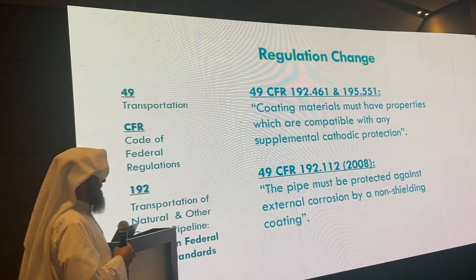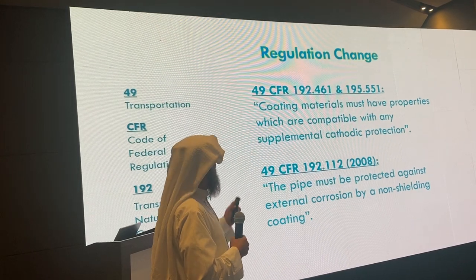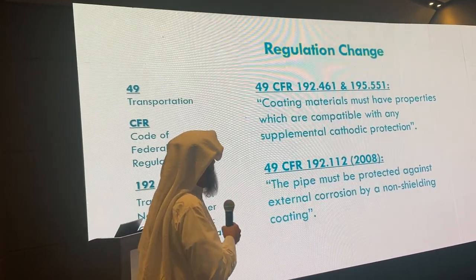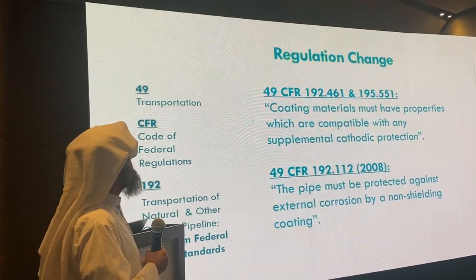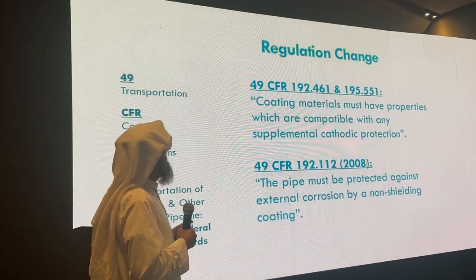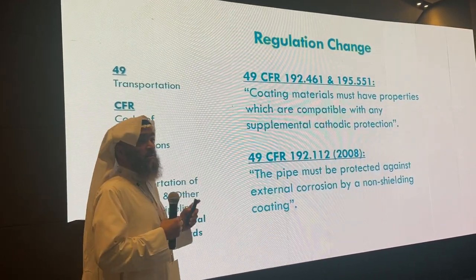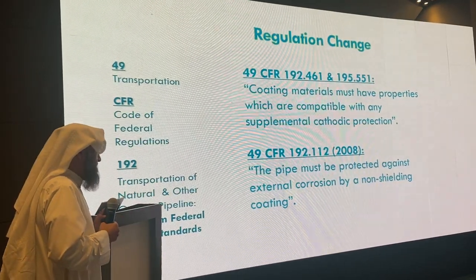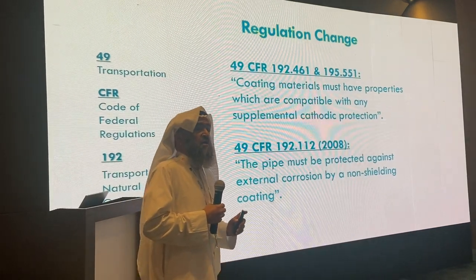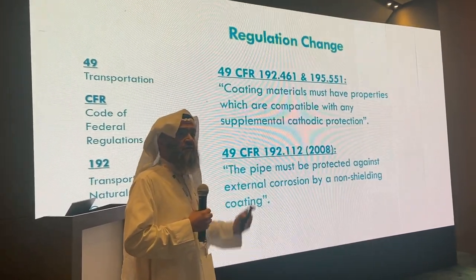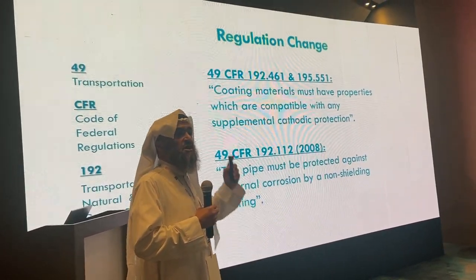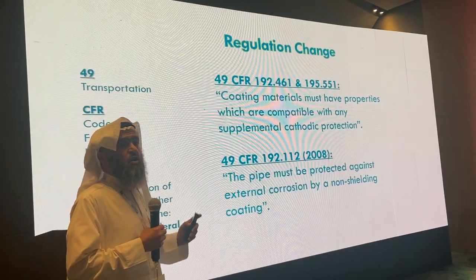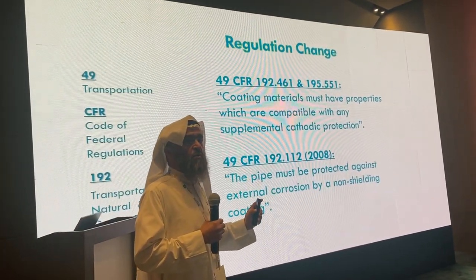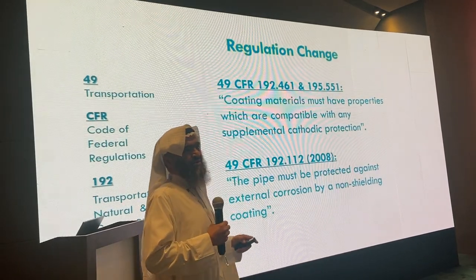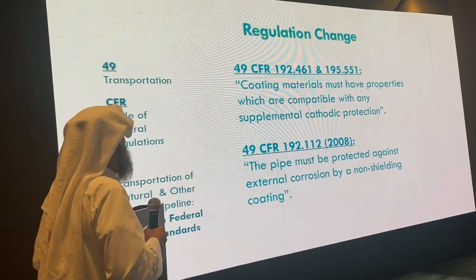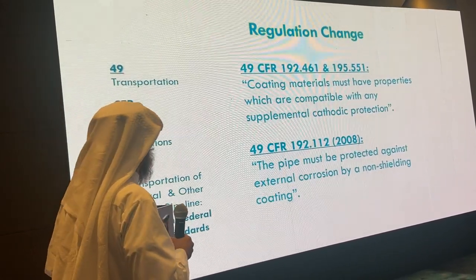In the Code of Federal Regulations in the United States, in 2008, they put these statements. Coating material must have properties which are compatible with supplemental cathodic protection. The pipe must be protected against external corrosion by a non-shielding coating. There is no single polyolefin tape allowed in the United States or Canada for maximum allowable operating pressure pipelines. They are not operating anymore there. They only operate in our area.